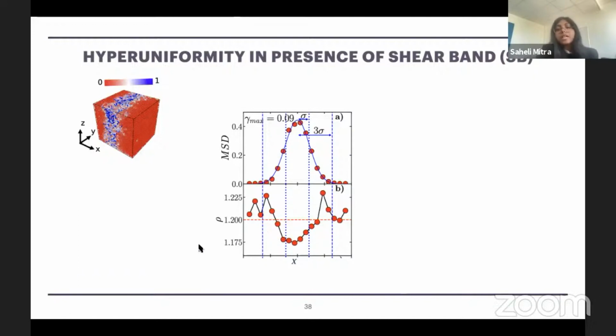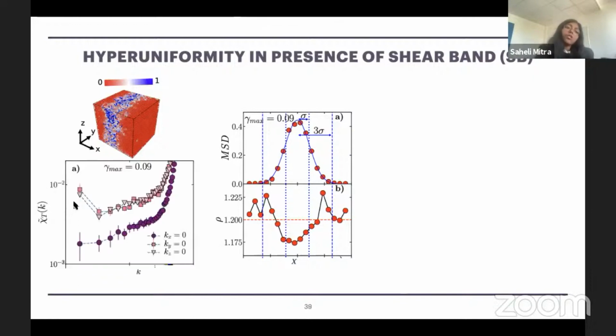observed by Anshul previously. So now we want to see if the upturn in the compressibility that we saw above yielding was indeed because of the shear band present in the system. How we do it is, instead of taking the wave vector k to be a 3D wave vector as a function of kx, ky, kz, we now choose three cases, one putting kx 0, ky 0, and kz 0. For kx 0, we are essentially computing the compressibility for planes which are parallel to the shear band, and we recover the hyperuniform trend. And for the planes which are perpendicular to the shear band, which is seeing the interface between the shear band and the part outside of it, we recovered the upturn.